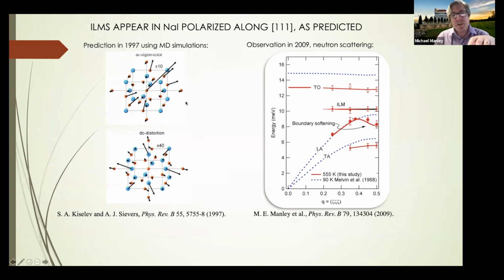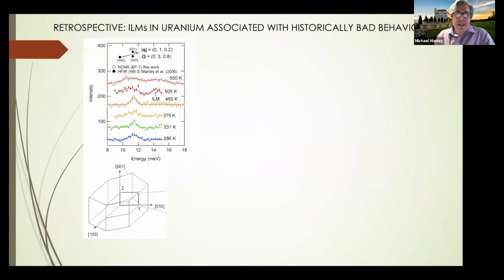And they made a prediction that it would appear there, and we went and we measured it, and the first time we found it. But it occurs at high temperature, so it doesn't exist at low temperatures. As you go up in temperature, this thing appeared in the gap. But ever since we did that, I've always been interested in finding some place where this kind of strange behavior is useful. I want to say something about nuclear energy, because I looked at this in uranium first, and it seemed like an interesting retrospective.